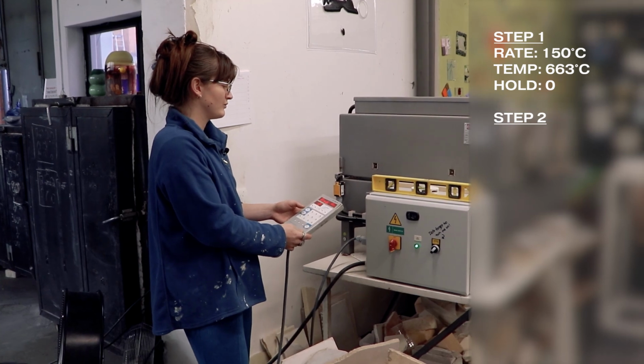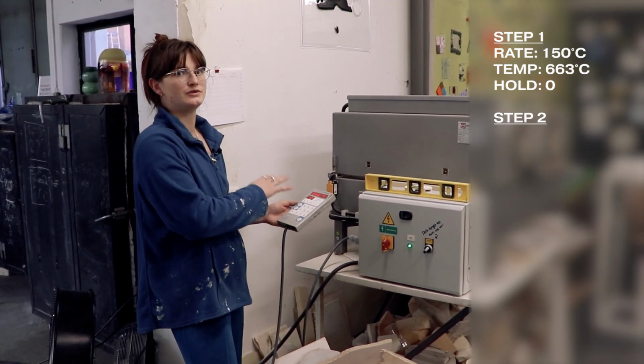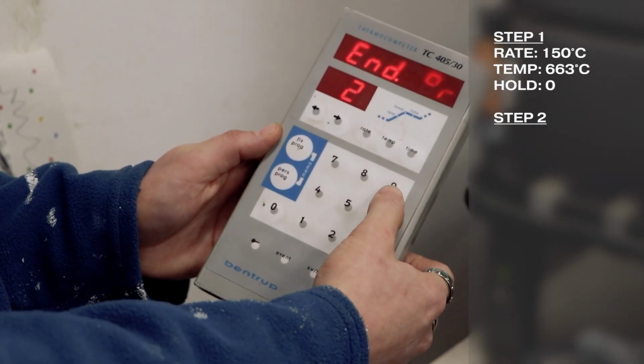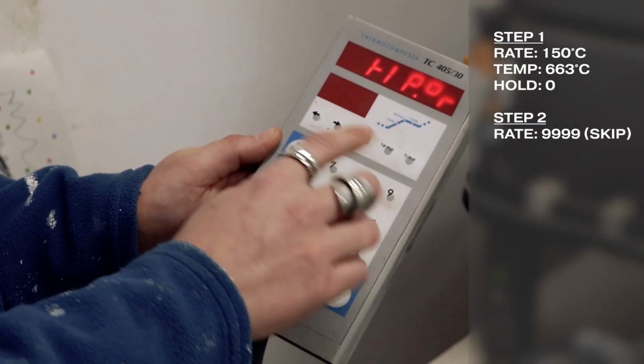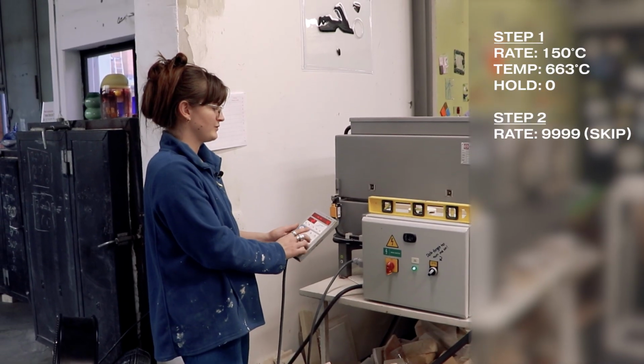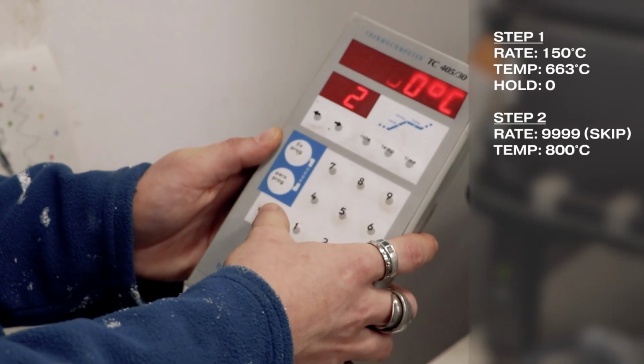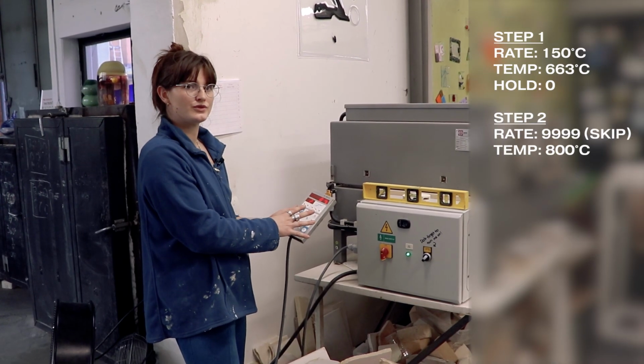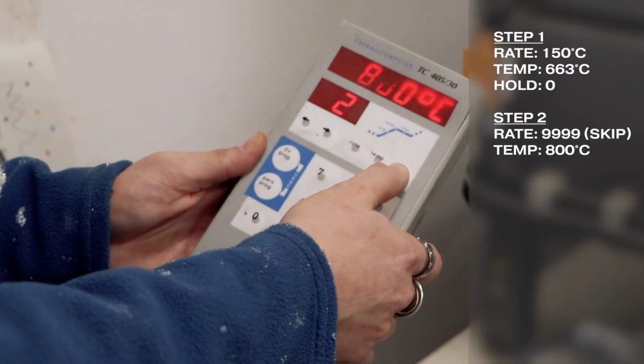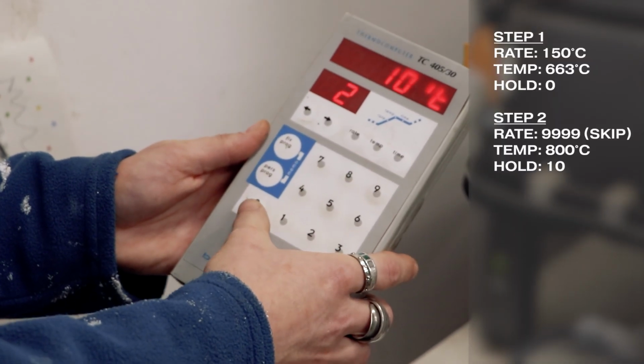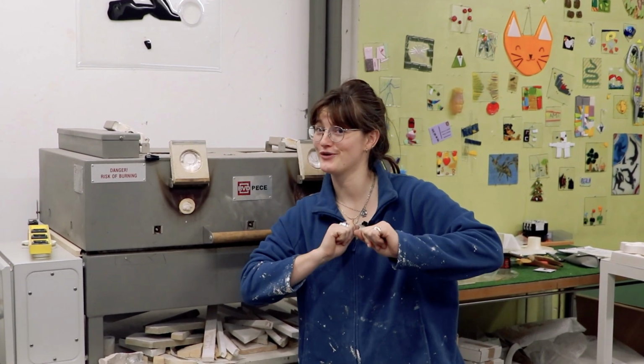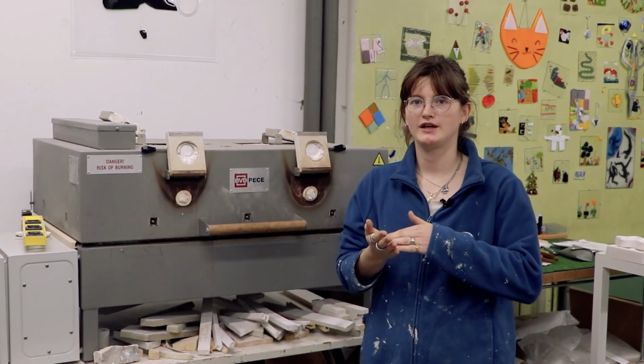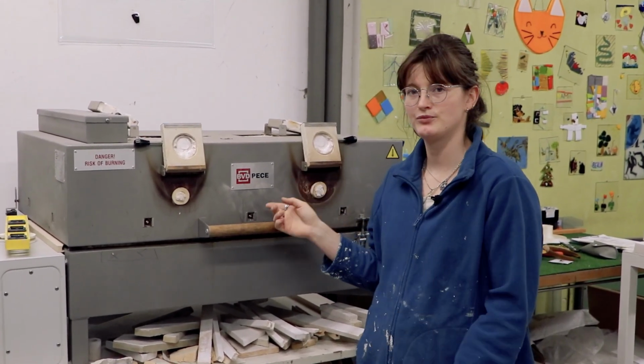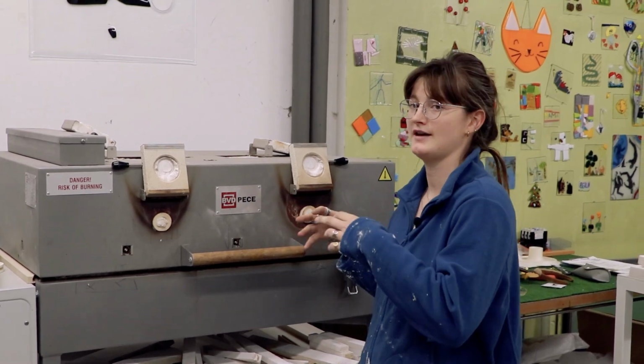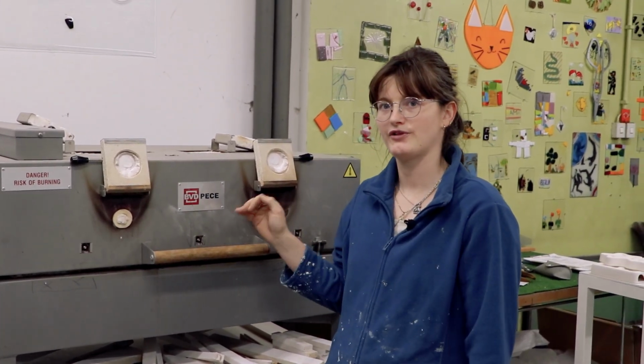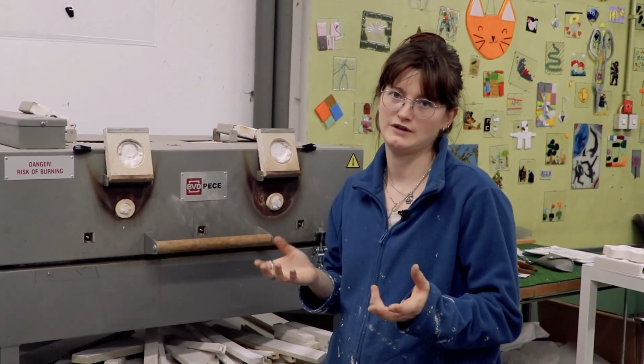The second step, we want it to go as fast as possible to the temperature. So as fast as possible for us is 9999. So it's a skip. So as fast as possible, I want to reach 800 degrees. That would be my top temperature, so the highest part of my firing. We want to hold there for 10 minutes. Wait, there's something you should know. You have to make sure to calculate at what time you will reach top temperature to be present at that moment, to check on your firing and make adjustments if needed.